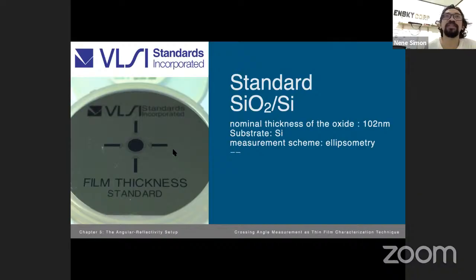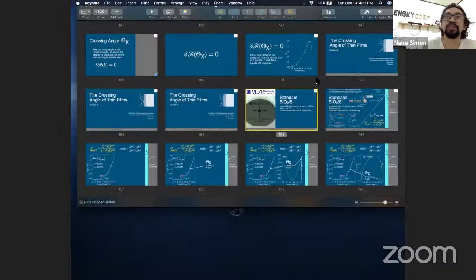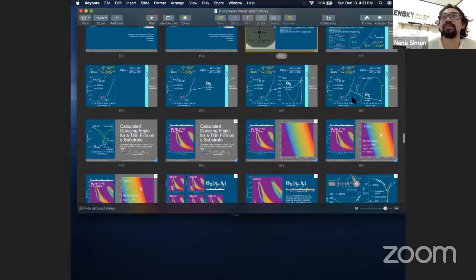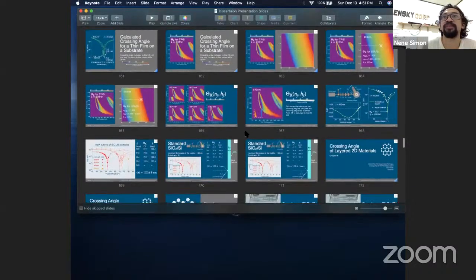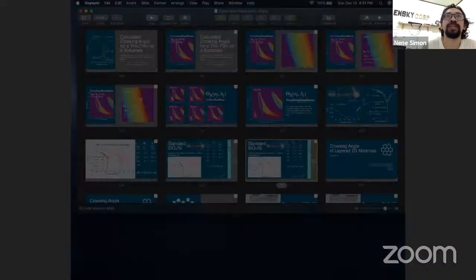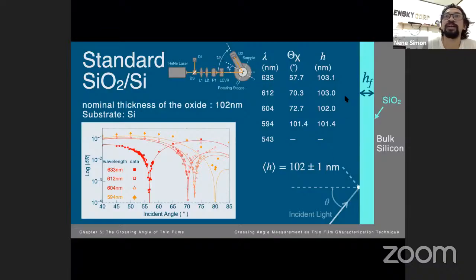Yes. The uncertainty I reported is based on the measurement I performed. The uncertainty of plus minus 1 nanometer is based on measurements with different HeNe wavelengths. The average of these four measured thicknesses is 102, and the plus minus 1 is based on the largest deviation from the mean.